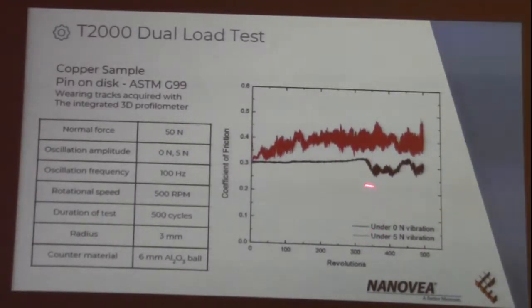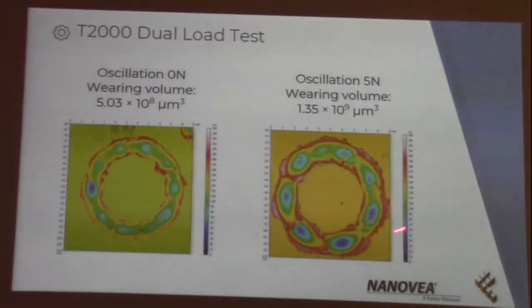So in this case, in black, we can see a copper sample, the base sample, on the same kind of test, with 0 Newton vibration superimposed and 5 Newton vibration superimposed. If we look at the 0 Newton, we have a plateau area in which simply wearing occurs. Then we have the production of third-party material inside our wearing tracks that starts to lower the friction, and then we have several fatigue events. And if we apply 5 Newton, we can see that the friction coefficient starts to rise higher, and we have much higher fatigue, and the wearing volume is maybe 2 times more than in the case of no superimposed vibration.